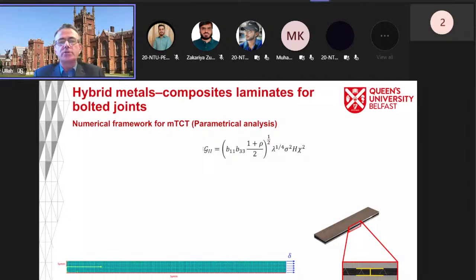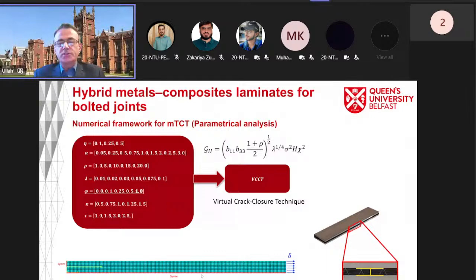So we run about 20,000 simulations with all these input parameters. So we do some parametric study. And then we create this type of FEA model. As you can see, this is just a quarter of the sample which we can generate because of the symmetry. And here we are using the virtual crack closure technique, which is VCCT.